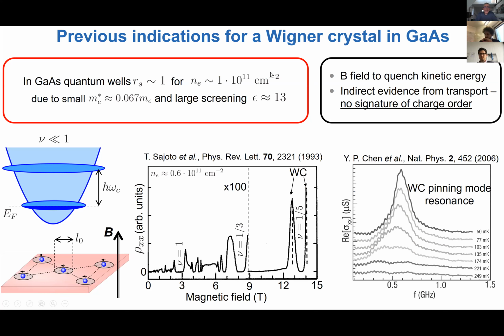Most of the efforts focused on gallium arsenide, and the problem with gallium arsenide is that this r_s parameter, even at low densities, is on the order of 1. The reason is that the effective mass of electrons is very light, which makes the electrons have a high mobility but reduces r_s, and the dielectric screening is gigantic. So the community has primarily focused on applying a magnetic field, which creates Landau levels with a large separation owing to the light effective mass. The end result is that one can quench the kinetic energy and confine the electrons into the lowest Landau level. And then in this system, one could hope to get signatures of a Wigner crystal.